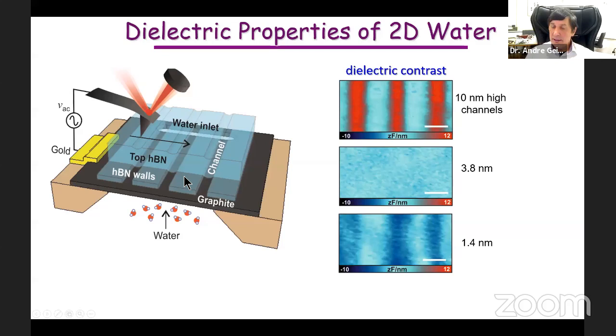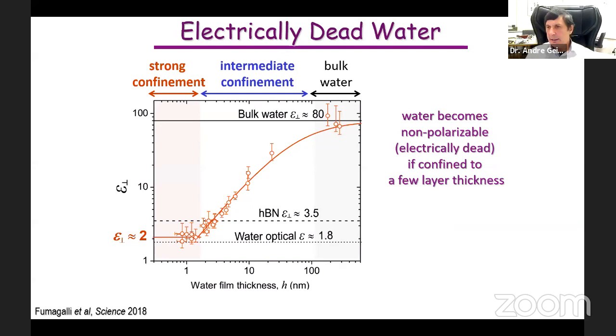Everything can be quantified in terms of perpendicular dielectric response. And this is a summary of our results. We see that from bulk values, we gradually get smaller and smaller dielectric constant, and then it saturates for capillaries of about 1 nanometer thick. Essentially, water becomes electrically dead, at least in one direction.